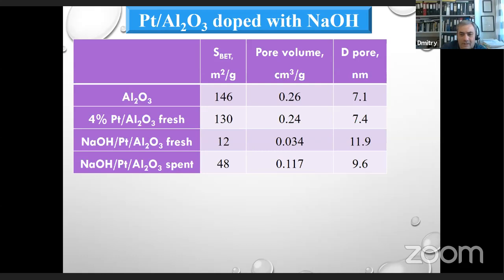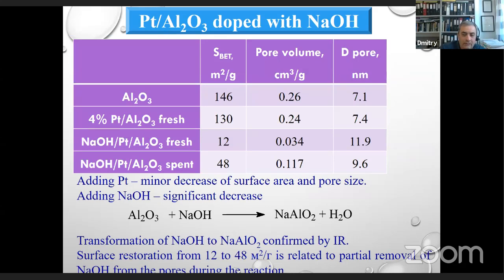When we introduce sodium hydroxide on platinum on alumina, the surface area decreased. That was also the same with the pore volume, which also decreased after introduction of sodium hydroxide. In the spent catalyst, we had an increase of surface area and the pore volume, which we attributed to partial removal of sodium hydroxide from the pores during the reaction. So adding sodium hydroxide to the catalyst, in fact, resulted in formation of sodium aluminates, which was confirmed by infrared.